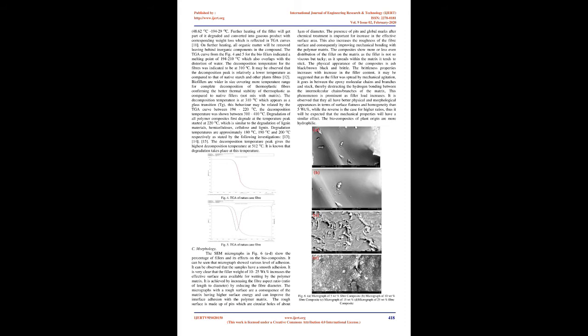The peak that appeared at a frequency of 1360.5 cm⁻¹ indicated the presence of C-H of alkanes. The peak at 1230 cm⁻¹ indicated the presence of C-H, CH2X stretch of alkyl halides. The peak at 1028.7 cm⁻¹ indicated the presence of C-N stretch of aliphatic amines.